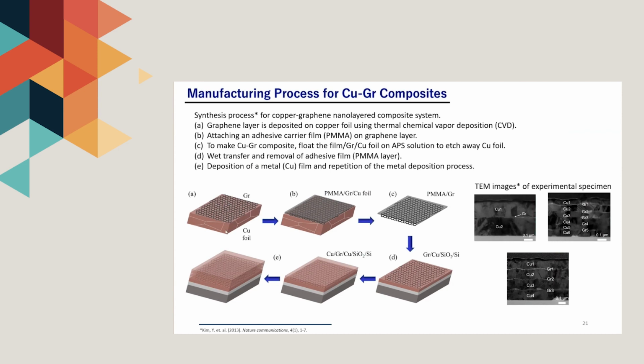Graphene layer in the copper foil, grown using thermal chemical vapor deposition. TEM images indicate the different layers of composites, such as one layer of graphene sandwiched by two copper layers, shown in the top left corner.